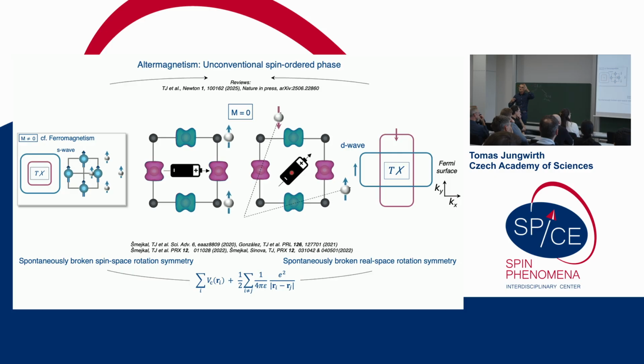Okay, so it now depends which way you apply bias with respect to your crystal, and you can either have different magnitudes of the electrical currents in the two channels, or you can have different deflection angles. And this is a consequence of this anisotropic deformation of each individual Fermi surface. This makes the transport anisotropic, but also the mutual rotation of these deformation axes can result in these different magnitudes or different deflection angles for the two spin channels.